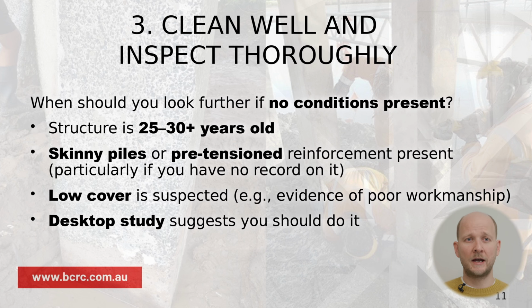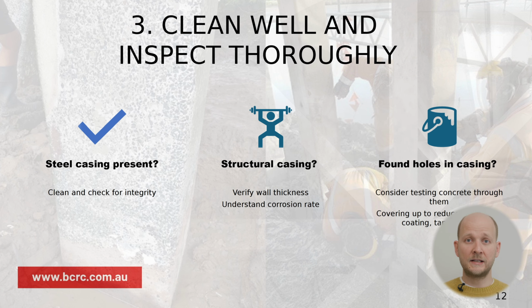When you suspect low cover, I would typically look at the workmanship of the entire structure, and if you suspect poor workmanship, that's a good sign that there might be some spots with very low cover, especially near the water. If you're dealing with steel casings, clean them as well and check for integrity. If it's a structural casing, if you don't know, assume it is structural or consult with the engineers. I suggest you verify wall thickness and understand the corrosion rate and whether this casing still provides adequate performance to the entire structure.